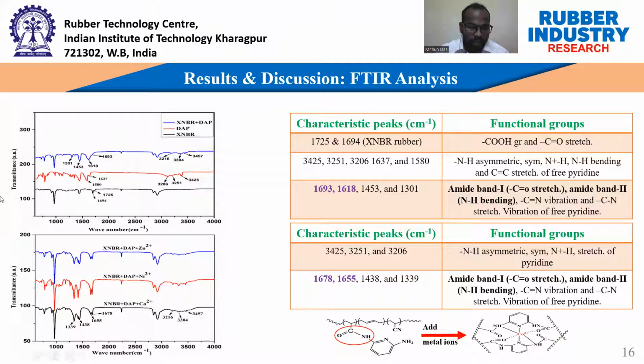The characteristic peaks are at 1725 and 1694, mainly the COOH group and the C=O stretching. And this is the pure DAP ligand. After the addition of DAP ligand, what happened? The amide linkage was formed, which is confirmed by 1693 and 1618, mainly amide band 1, the C=O stretching, and amide band 2, that is the NH bending. So the amide linkage was successfully formed inside the rubber matrix.